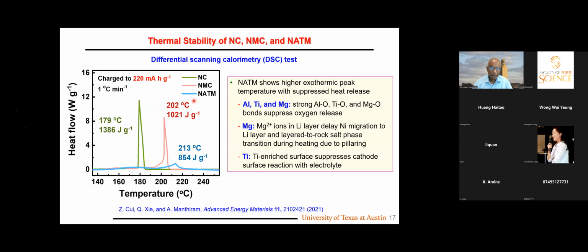The same kind of trend, NC, the lower temperature, more heat release, NATM has the highest temperature and the least amount of heat release. And you can understand that when you have these ions, they form stronger bonds, a little bit stronger compared to cobalt oxygen or nickel oxygen. The metal oxygen bond can very easily break with cobalt oxygen and nickel oxygen.